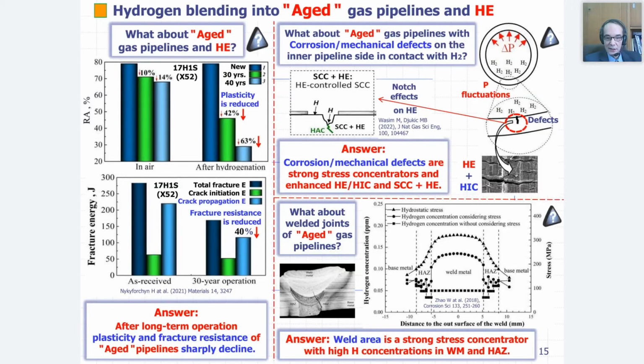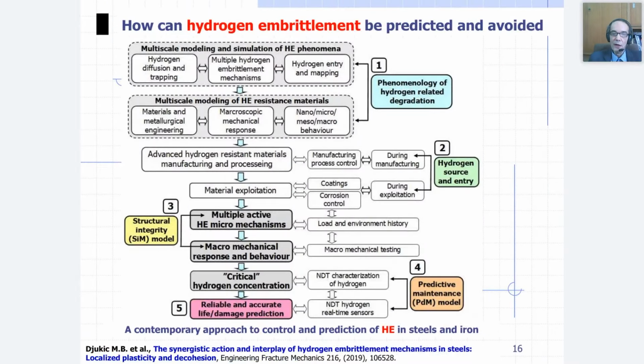So the answer is that weld area as a strong stress concentrator represents the area with a very high hydrogen concentration and also prone to hydrogen embrittlement, particularly weld metal and heat affected zone. So how can hydrogen embrittlement be predicted and avoided? That's the most important thing for industry.